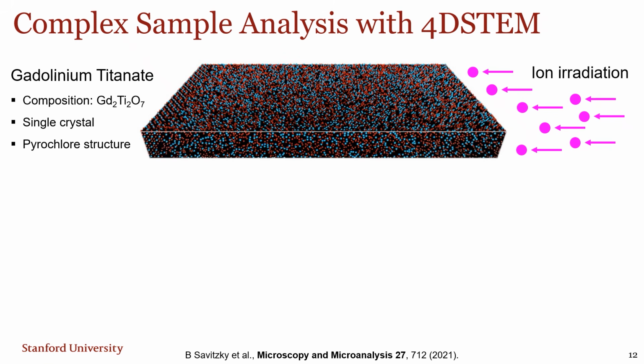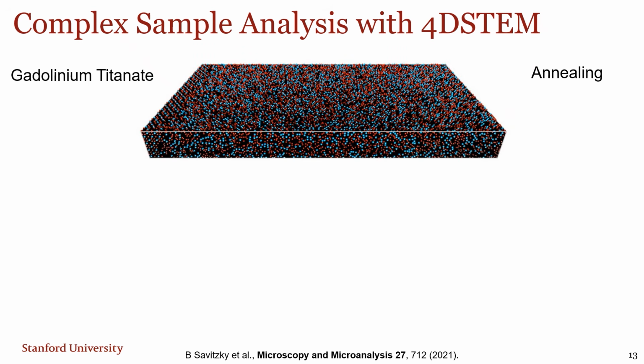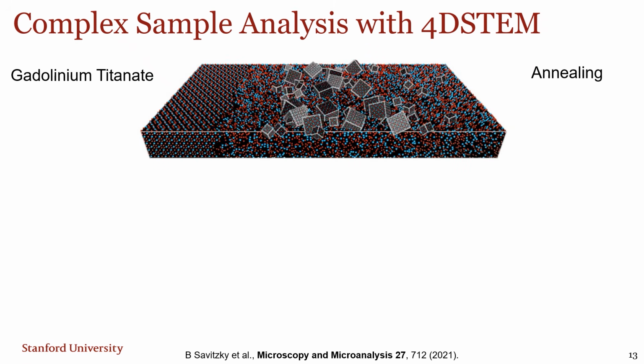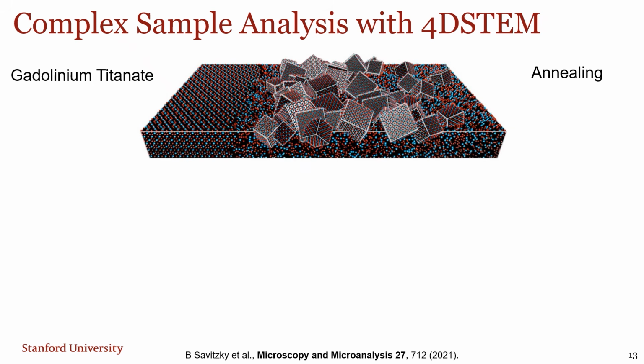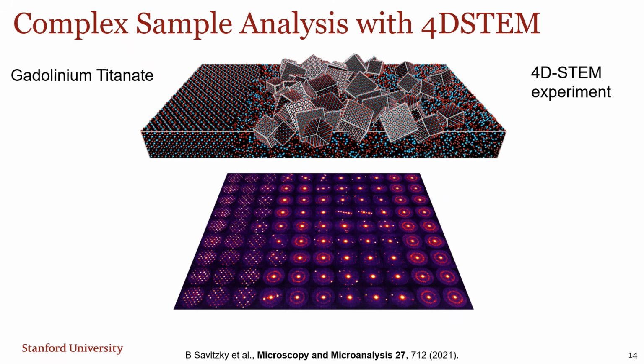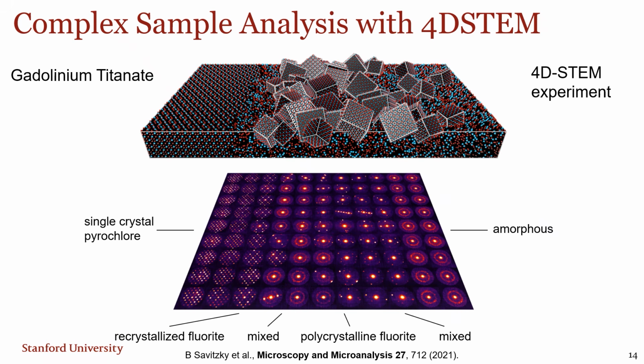Now, of course, they want to have a lifetime of these materials of, say, 20 years. We don't have enough time to wait, so instead they anneal it at higher temperature to see what the sort of long-term reaction of this material would be. And what you see is you recrystallize into the amorphous front, but you also nucleate a bunch of randomly oriented polycrystalline grains. So what I want to show you is all the diffraction patterns that we record from a sample like this. And just by using what you saw in the toy models in the previous slide, you can see we're able to figure out what regions are single crystal pyrochlore, the original structure, recrystallized fluorite, or these amorphous or disordered regions of the sample here.